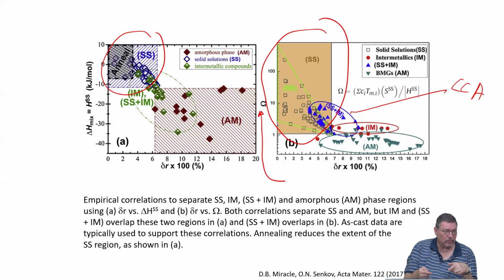This can also be put into the CALPHAD code, so you can have these virtual phases, I would call them, so they were only calculated, also put in. This is then ab initio informed CALPHAD. If you put in experimental data, it's experimentally informed CALPHAD, but better to do both if possible. You will still miss maybe some of the intermetallic phases, but they would probably have very complex or rather complex crystal structures, because then you need larger elementary cells, and this is computationally more costly, so people avoid to do that. But they would also form much slower, so the probability that these form is lower. So I mean, if you first to start with have an experimentally informed database for CALPHAD, and then you calculate based on these phases which should exist, it's, I think, a very good start.